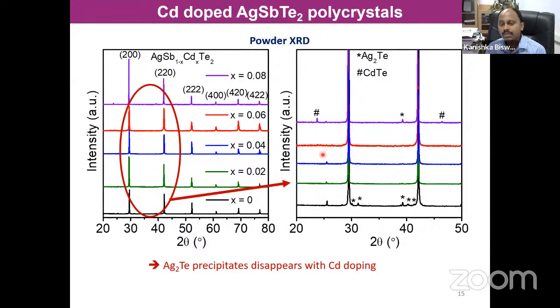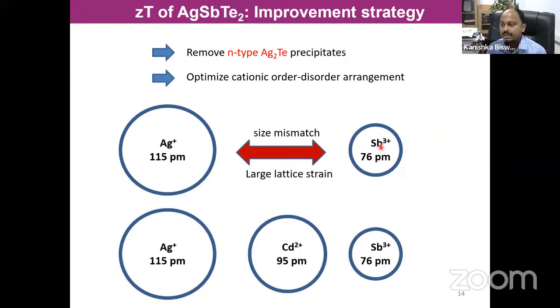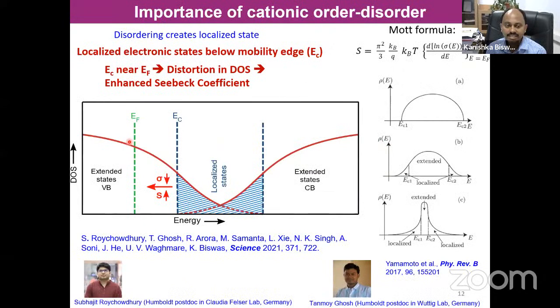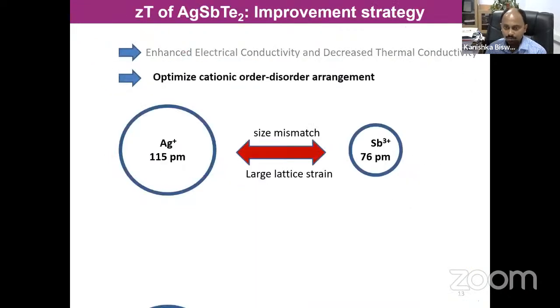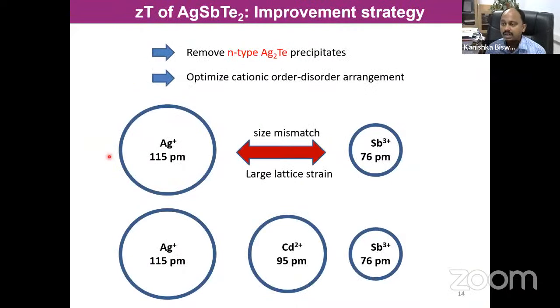Another way to think about why we chose cadmium is that cadmium is 2+. We are doping cadmium in the antimony position, and antimony is +3. If I dope +2 in a +3 position, it creates one extra hole. Once it creates an extra hole, I am doping holes in this system, and my Fermi level moves to the left, away from the mobility edge, so we have extended transport. That way we can also think this +2 doping is good in place of antimony, not in place of silver. That is a logical way of thinking about which doping element to choose to tune the Fermi level to the mobility edge gap in this solid.